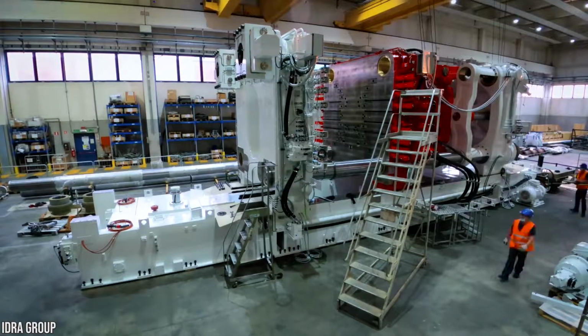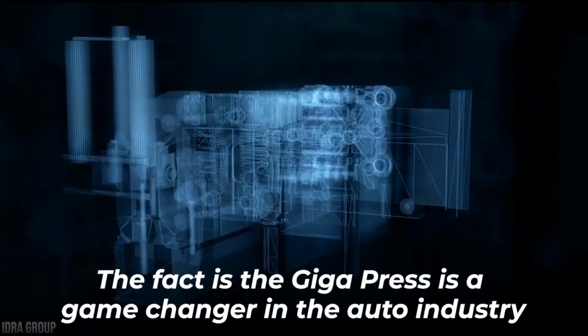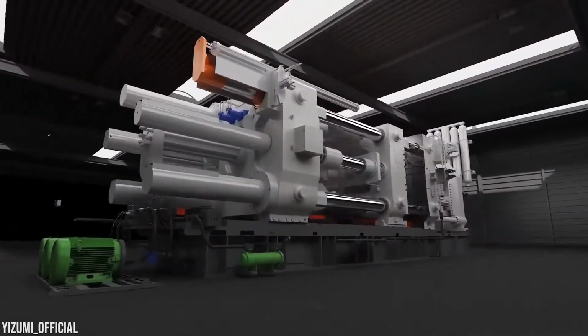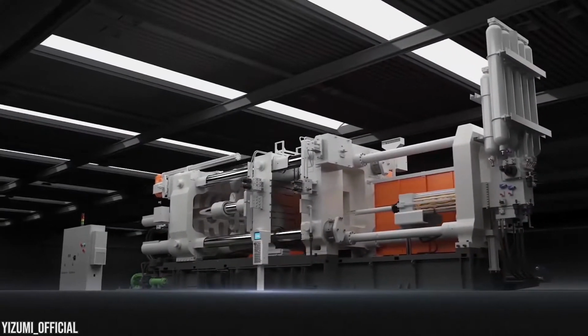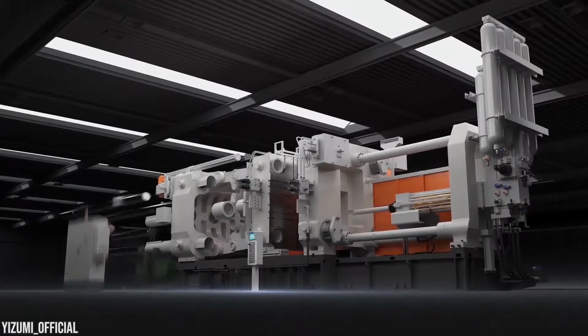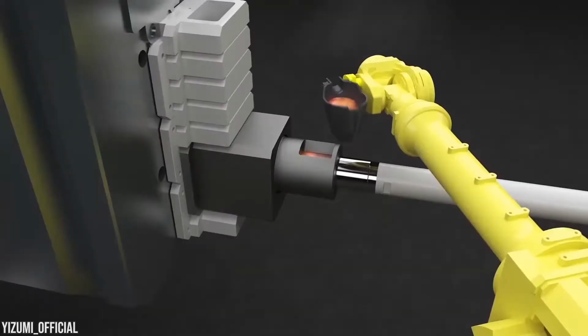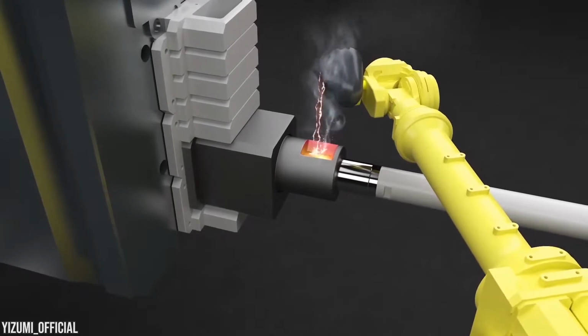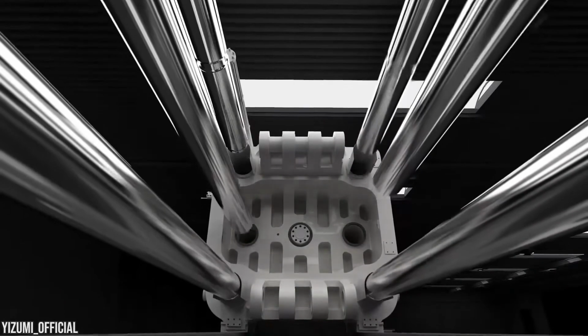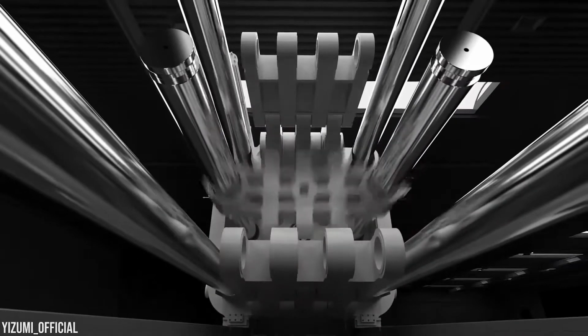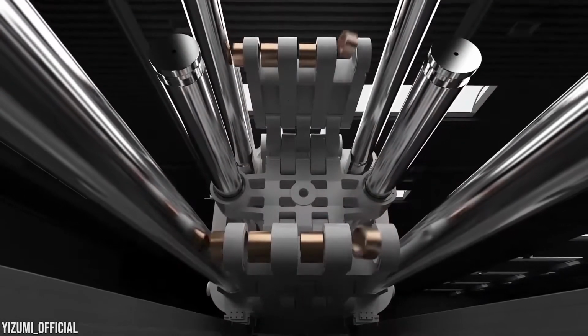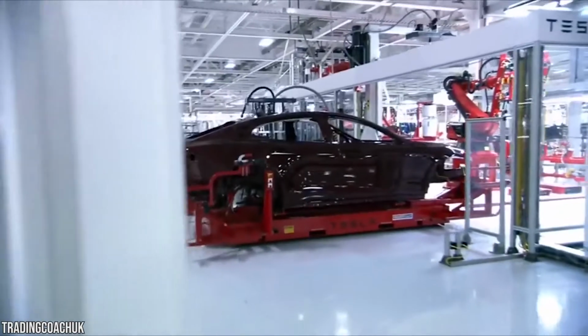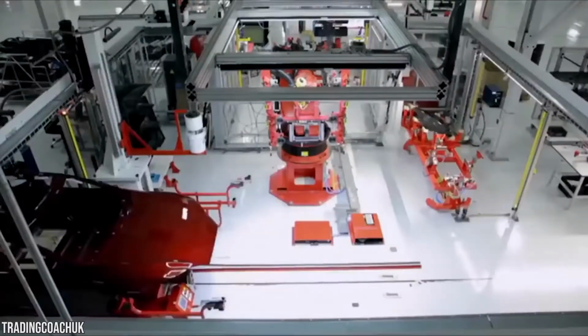Gigapresses require a lot of investment in space for installation, so Tesla must have seen the clear benefits before committing to them. The fact is, the Gigapress is a game changer in the auto industry. The most obvious advantage is speed, because despite their great proportions, they work very fast. Per IDRA specs, the aluminum silicon alloy can go from molten metal to a chassis in less than 100 seconds, and that's a blistering speed when you compare that to all the steps and labor involved in fabricating and fastening more than 100 parts together. It simply means Tesla can make more cars than the rest.